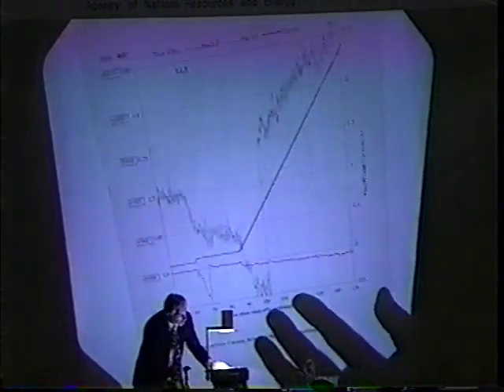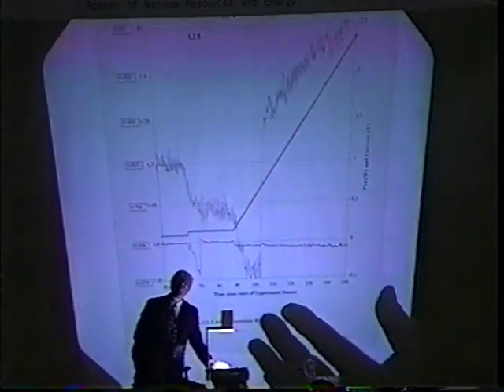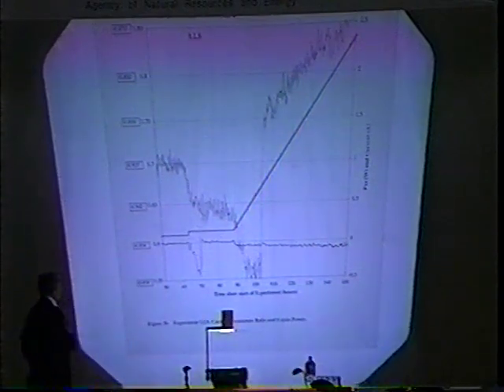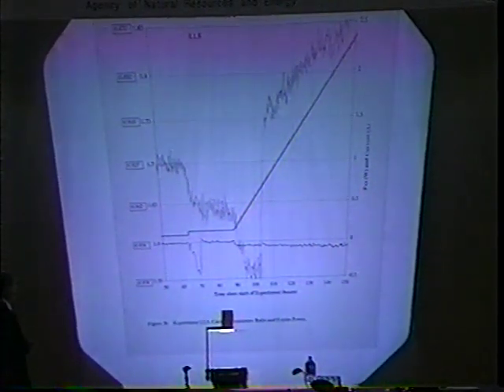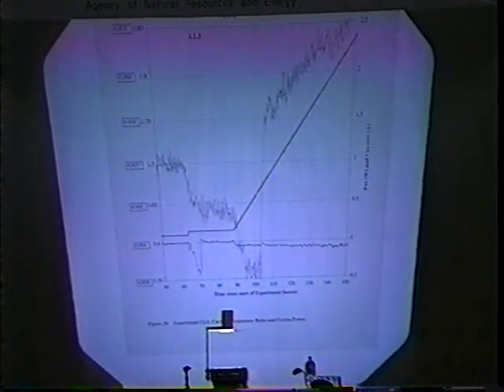portion of the graph, this is actually set out on the same time window, 100 hours, as the first graph. You can see the features that I was talking about. It was loaded to 0.927. We stepped the current up, it loaded to a value of about 0.95.